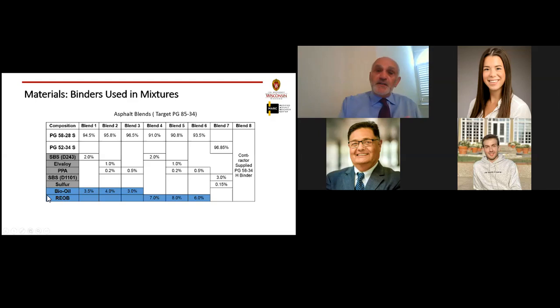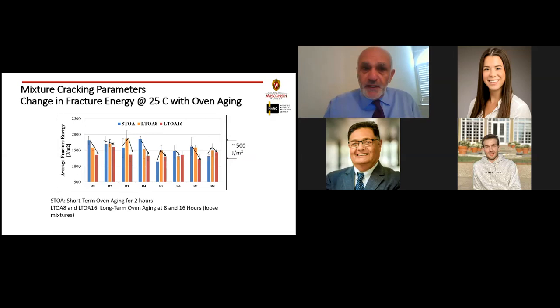So here's the first set of very simple data. Short-term aging of mixtures, long-term oven aging for 8 hours, and long-term oven aging for 16 hours. And these are the fracture energy. If you look at these, what's interesting, all of these mixes with very different types of binders, the range is so small, only 500 joules per square meter, which is a very, very small range. You can see the variability of many of these mixtures is within that range.